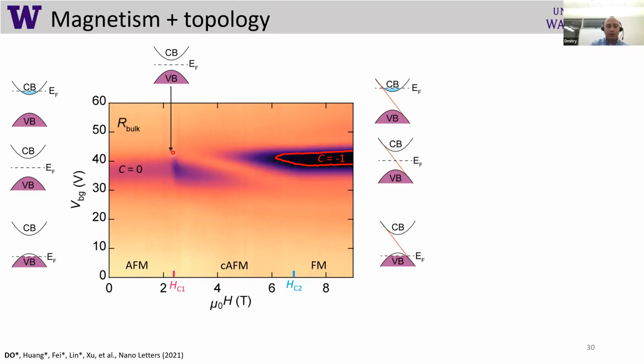So when we increase magnetic field, we can see a kink right here in the insulating state. I'll remind you that yellow is conducting and this dark red or dark purple is insulating. So we can see that at this point near HC1, we see a kink and movement towards the bottom. So essentially our gap, which was flat here as a function of magnetic field, starts to go down and decrease. In this case, we can see that the material is not gapped anymore. We always have conduction, even though we have an insulating state here, now it conducts all the time. It is an indication that when we change magnetic state, some of our bands touch and band inversion happens. So when band inversion happens, an inverted gap starts to open, and then you start to have a non-zero Chern number.